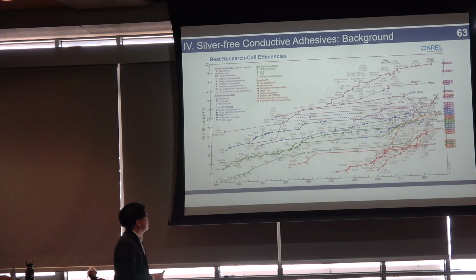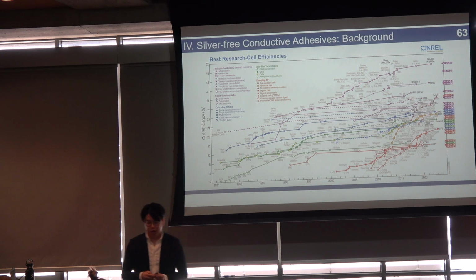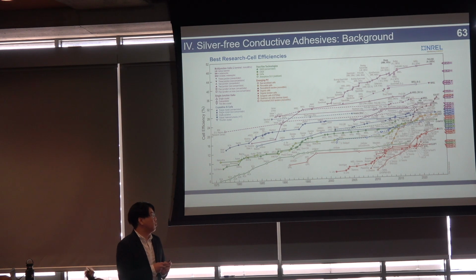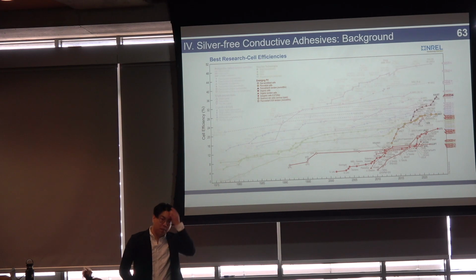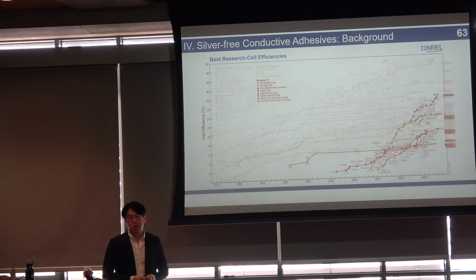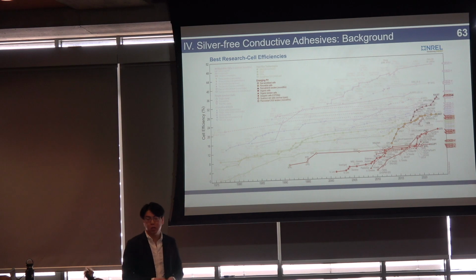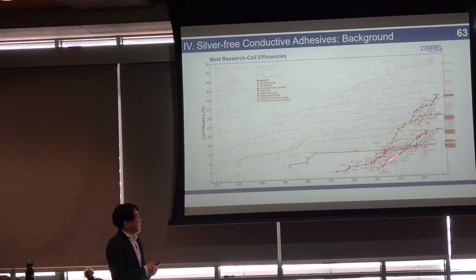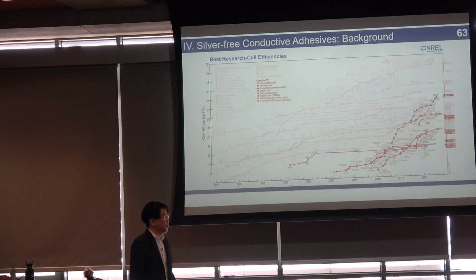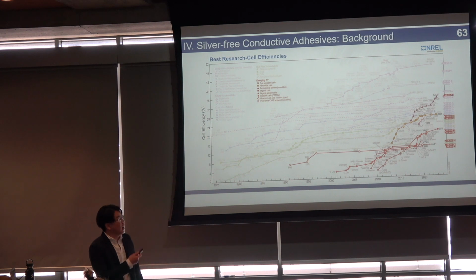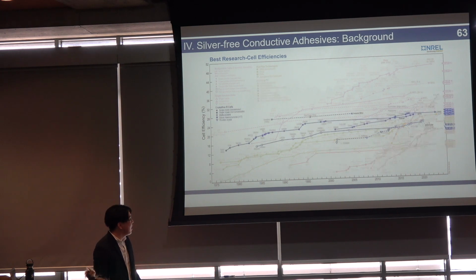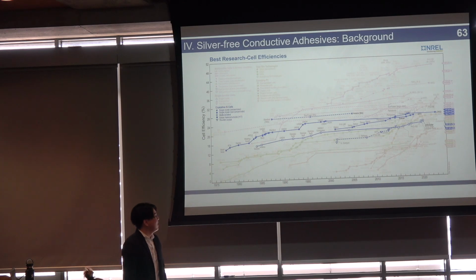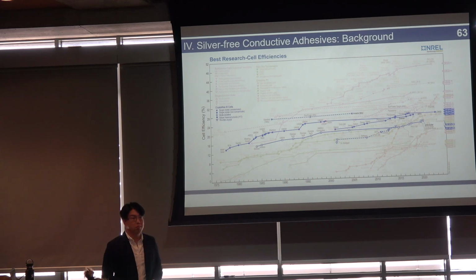We can look at the efficiencies of modern solar cells, which is actually kept track of by the National Renewable Energy Laboratory. And we can look at a couple different classes of materials. For example, normally I work with a class of photovoltaics called emerging photovoltaics. These are organic photovoltaics or perovskites. And you can see that the efficiency of these devices has increased very, very quickly. Perovskites 10 years ago had a maximum efficiency of about 13%, and now they're at 26%, so it's doubled in 10 years. But silicon, unfortunately, doesn't have that trend. A lot of silicon seems to have flattened out in terms of efficiency.